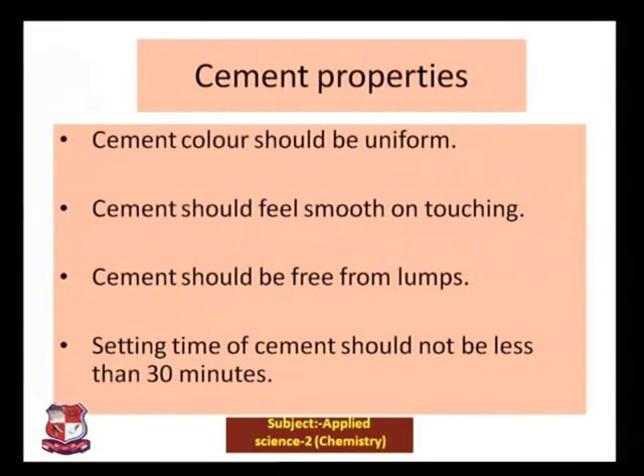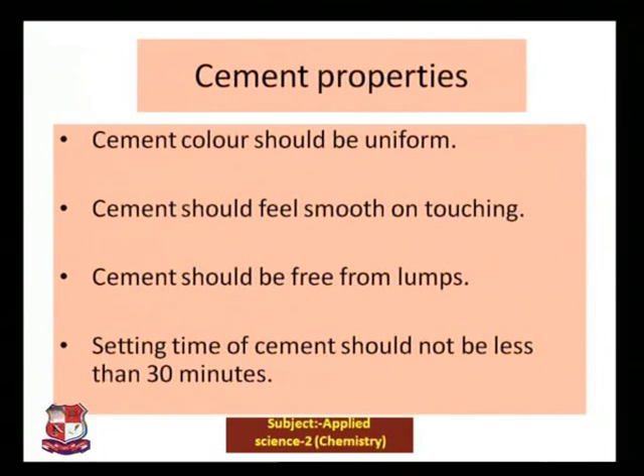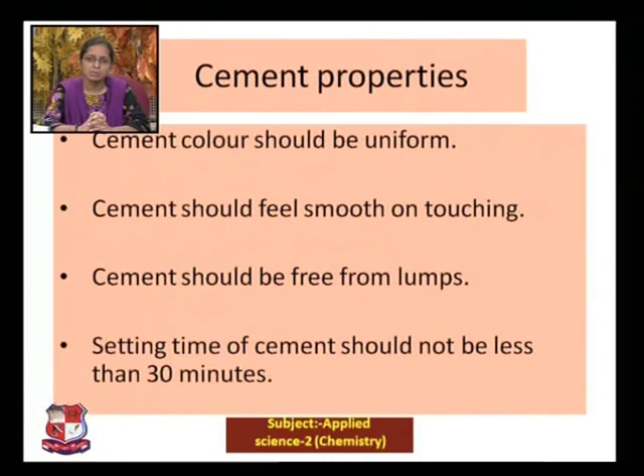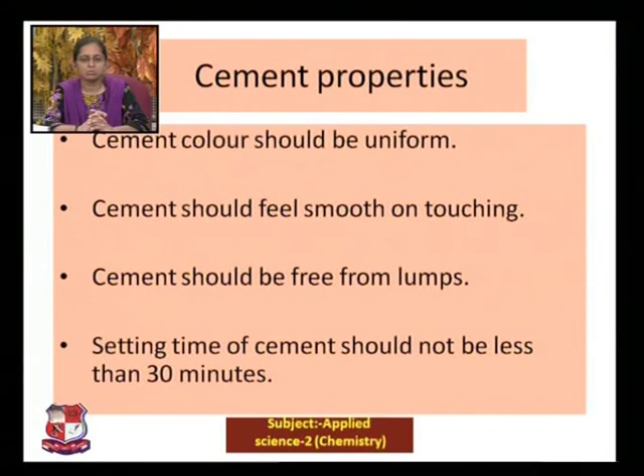Let us discuss the basic properties of cement. The color of cement should be uniform in appearance. It should feel smooth on touching. Cement should be free from lumps — there should be no aggregate formation. The setting time of the cement should not be less than 30 minutes. If setting time is less than that, cement will harden very quickly, which is not desirable.